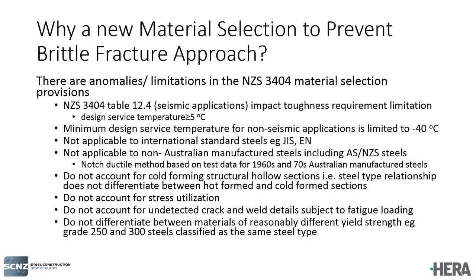The requirements do not include overseas steels like Japanese and European steels. They're not applicable theoretically to those steels. And they may not be fully applicable to AS/NZS steels manufactured overseas because they are based on test data from steel manufactured in Australia in the 1960s and 70s. So there may be some limitations we don't understand. They don't account for strain hardening in hollow sections. They don't account for stress utilization, how much of the service load the structure receives. They don't account for any fabrication-related defects like undetected cracks, and they do not differentiate between materials of different yield strength, for example, 250 MPa or 300 MPa. Next slide, please.